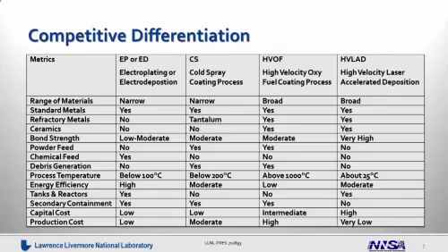In this particular table, we see a comparison of HVLAD technology to other coating technologies such as electrodeposition, cold spray technology, and a thermal spray process such as high-velocity oxy-fuel deposition. Unlike HVOF, HVLAD requires no powder feed. Unlike electrodeposition, no toxic chemicals are required. And unlike the high-velocity oxy-fuel process, HVLAD can be conducted in air at ambient temperature without the fear of phase transformations in the substrate or coating material.